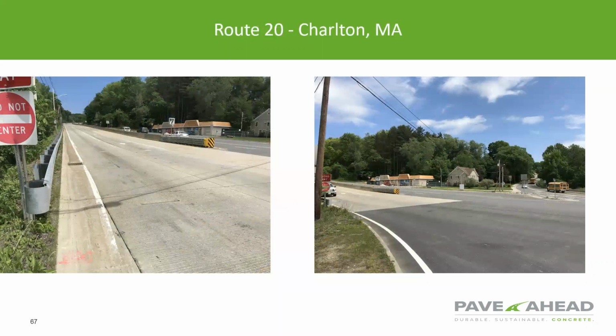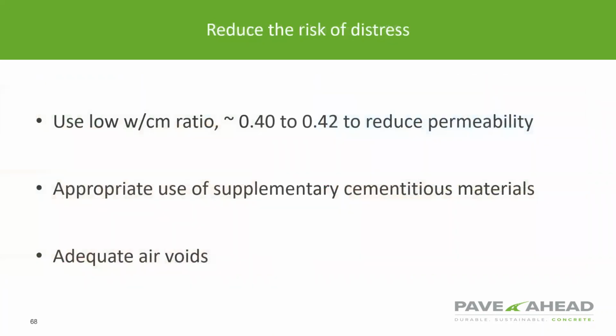Up in Charlton, Massachusetts, typically up in New England pavements, this was a project coming down the hill, and the pavement used an asphalt intersection. That asphalt intersection has been milled twice since the original concrete. On the left is the original concrete construction. So what are we going to do to reduce the risk of this in northern climates? We want to use a low water-cement ratio in that 0.4 to 0.42 range. Use the appropriate cementitious materials, whether it's slag.